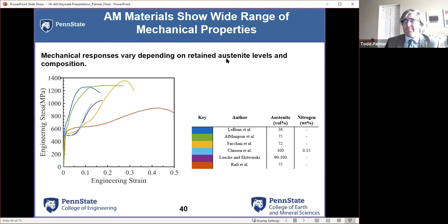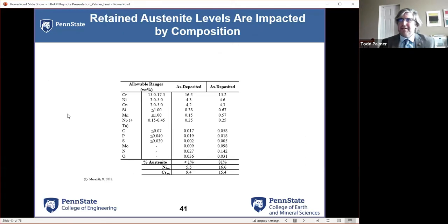And we found that these are based on retained austenite. PH grade stainlesses should have primarily a martensitic microstructure. We're going to find that if you add a lot of nitrogen to it, you start retaining large amounts of austenite. So you've got martensite and austenite. The austenite is going to transform with strain, so you end up with these TRIP type effects.